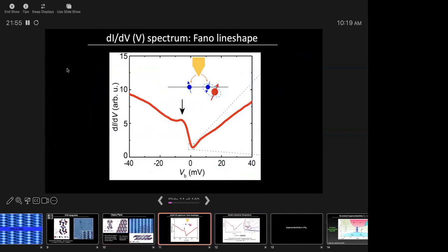Okay, so this is what the dI/dV spectrum at high energies looks like. This is pretty high energy scale, 40 millivolts. So you see this funny line shape, and many of you might be familiar with this line shape. This line shape is known as a Fano line shape. And it's a very peculiar line shape, and it arises because of a very interesting phenomenon, which is that when the electrons leave the STM tip, they have a choice. They can either go directly into this very high density of states band, or they can go into the continuum. And there's an interference between these two tunneling paths that leads to this funny line shape.